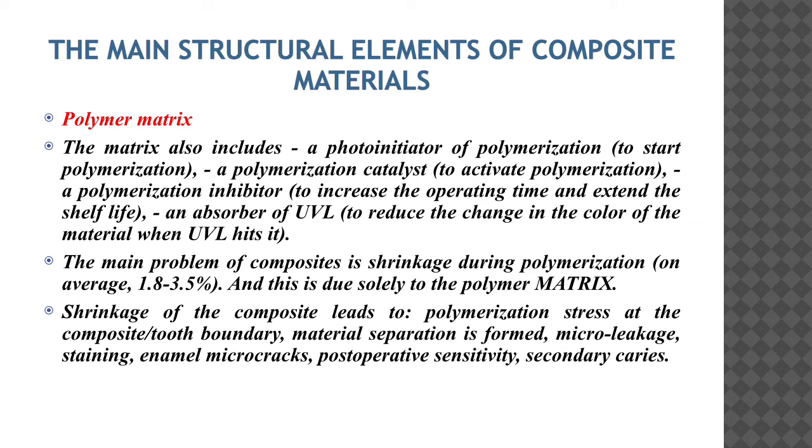Shrinkage of the composite leads to polymerization stress at the composite and tooth boundary, separation of material, microleakage, staining, microcracks of enamel, postoperative sensitivity, and secondary caries.